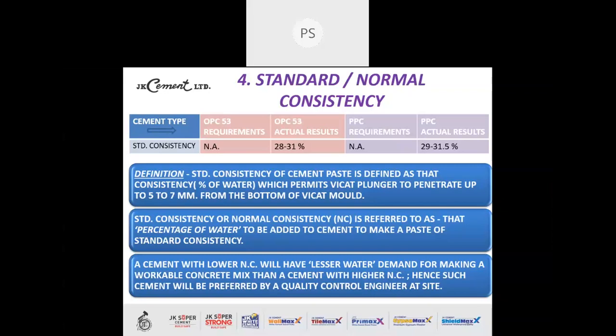Now we look at the definition of standard consistency. Standard consistency of cement paste is defined as that consistency or the percentage of water which permits the Vicat plunger to penetrate up to 5 to 7 mm from the bottom of the Vicat mold. This is the classic definition as per the IS code. There is an apparatus of the Vicat mold where you add the percentages of water and you get the desired standard consistency. Second point, standard consistency or normal consistency, NC, is referred to as that percentage of water to be added to cement to make a paste of standard workable consistency.